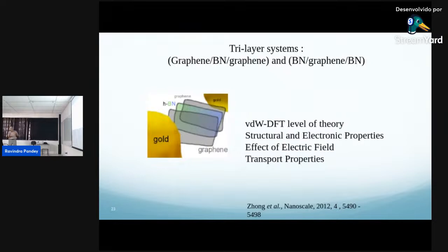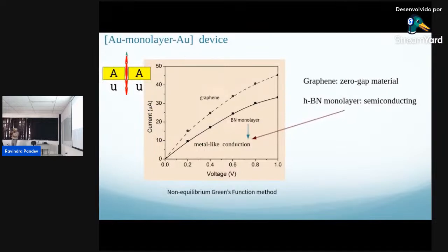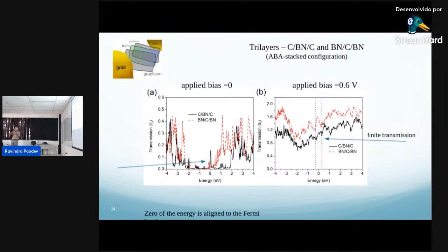Before that, we moved on from this monolayer system. So let's play with the 3-layer system and increase the thickness to see what happens. We looked at the left and right contacts, and instead of a monolayer, we have the so-called 3-layer system with different combinations. You look at graphene on top and bottom with boron nitride in between, or vice versa: boron nitride on top and bottom, graphene in between. And we are looking at the transmission function versus energy. The 0 is my Fermi level.